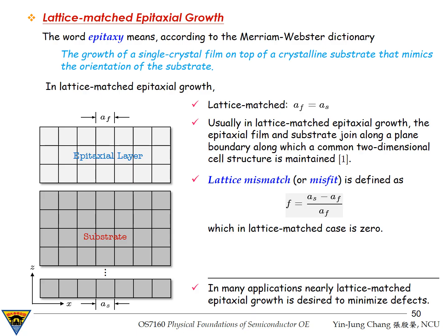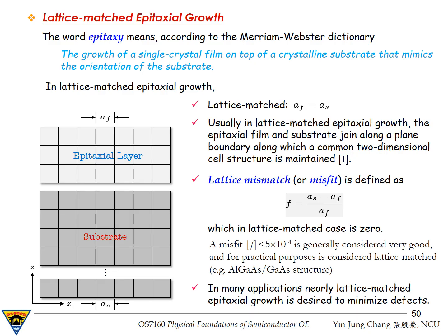Now, to quantify how different two lattice constants are, we define the lattice mismatch, or misfit, as shown in this expression. It is equal to the lattice constant of the substrate minus that of the film, divided by the lattice constant of the film. In practice, we rarely achieve exactly zero mismatch. However, if the magnitude of the misfit is smaller than 5 times 10 to the minus 4, we generally consider the system to be effectively lattice matched for practical purposes. A classical example is the aluminum gallium arsenide and gallium arsenide material system, which is extremely important for optoelectronic devices.